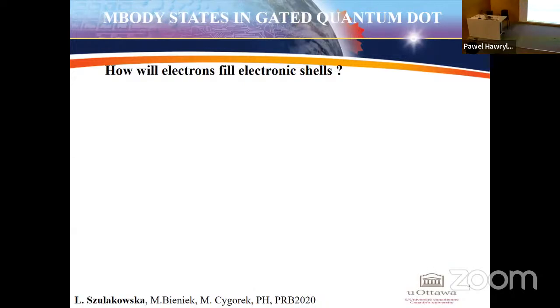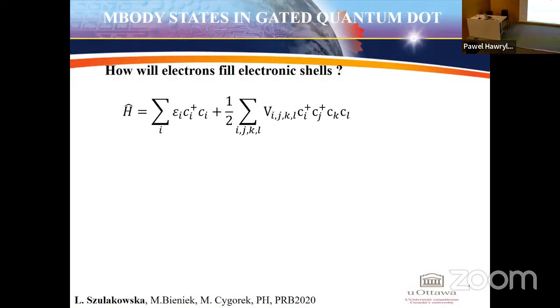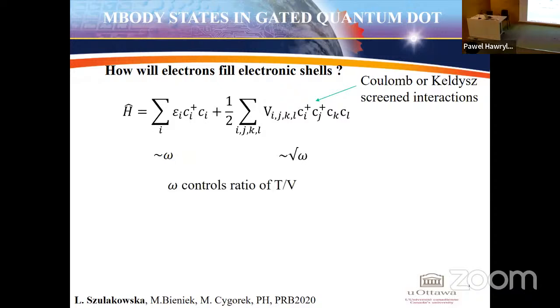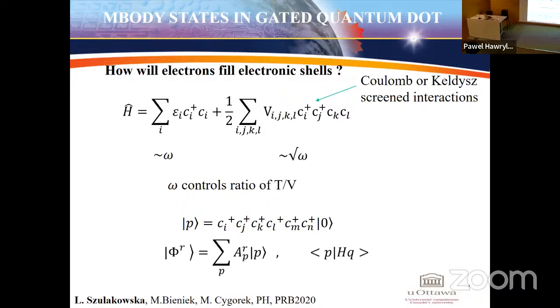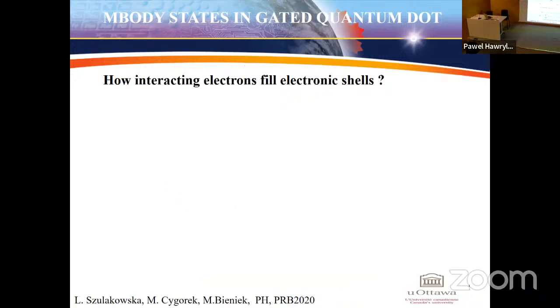And then the question is, how will electrons fill these electronic shells? Well, we do this by studying this interacting Hamiltonian. The Coulomb interaction is either directly screened Coulomb or Keldysh screened interaction. The kinetic energy is proportional to omega, the level spacing, while the Coulomb energy is proportional to the square root of omega. So by changing the level spacing, we can change the role of Coulomb energy versus single particle energy. So omega controls the ratio of T over V. We build configurations, we diagonalize our Hamiltonian and calculate ground and excited states.